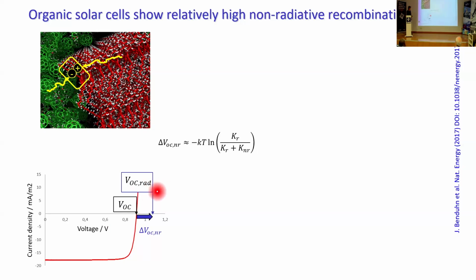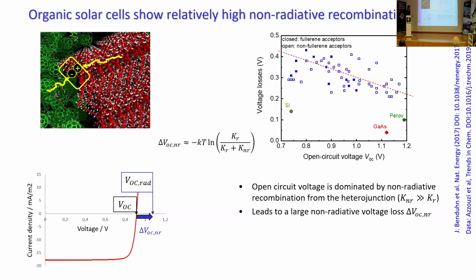And we can quantify it by working out what open circuit voltage the material that we're using should have if it were working perfectly, which is in what we call the radiative limit. And we can look at the difference between the actual voltage and that perfect value, and that should be related to the relative efficiency of radiative and non-radiative recombination processes. And if we look at this for the case of organic solar cells, that gives us data like these blue dots over here.